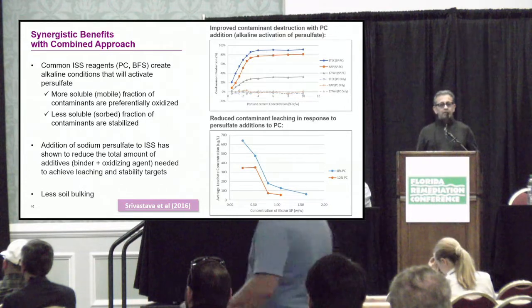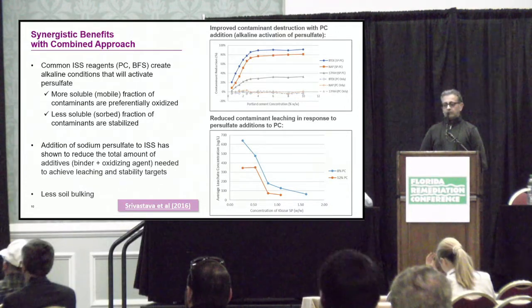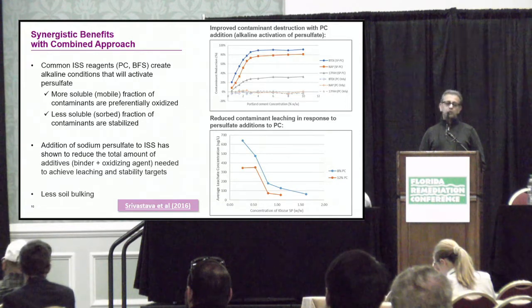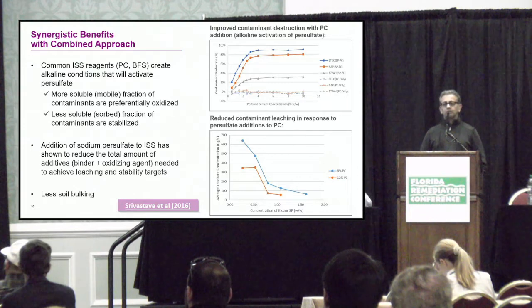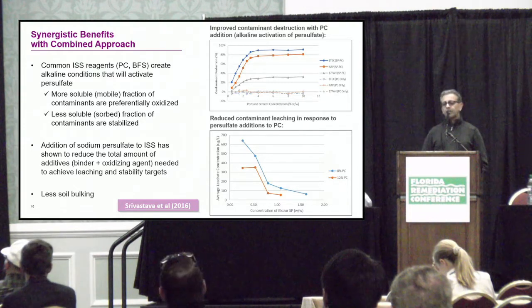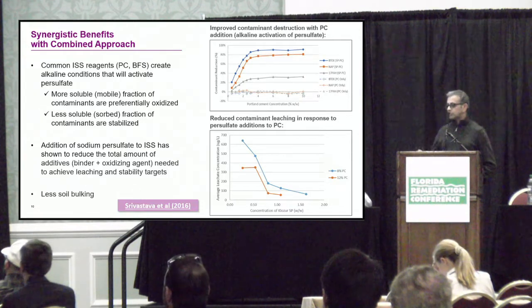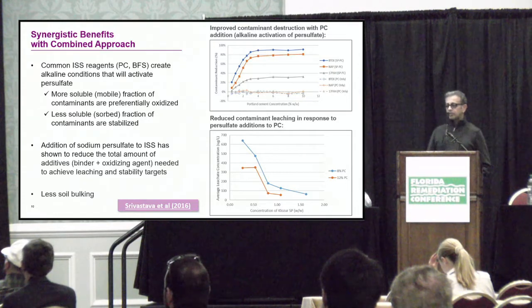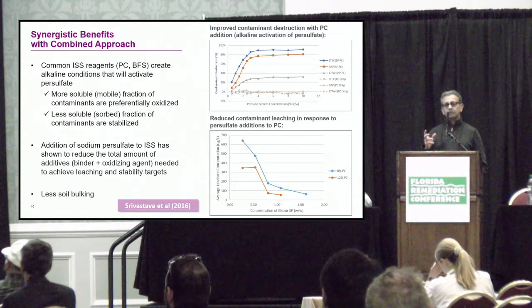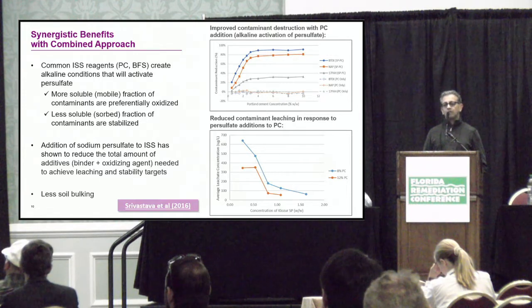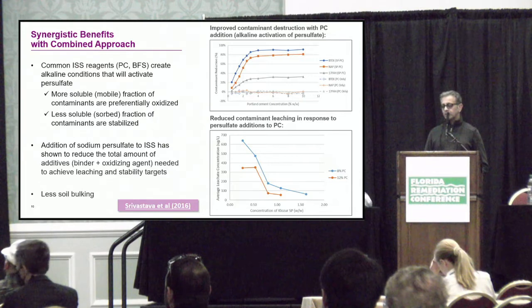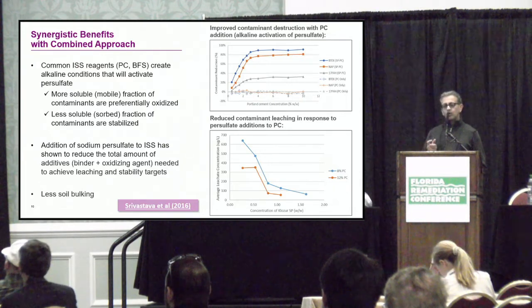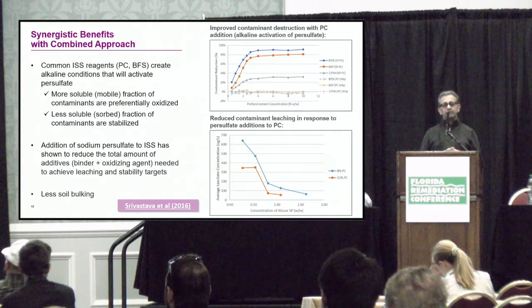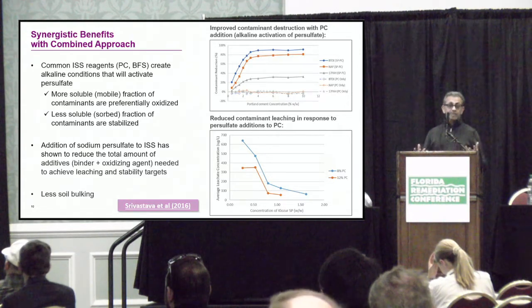So what happens when we combine the two technologies together? This was in 2016, Srivastava et al., who is now with Burns and McDonnell. He did a lot of the initial work in the lab to demonstrate that combining the two technologies has a lot of merits. And this slide presents some of the data from his study. Essentially, the more soluble compounds are first preferentially degraded, and the less soluble or less available contaminants are entrapped and stabilized in the ISS matrix. He also demonstrated that adding small amounts of persulfate to the ISS mix reduces the total amount of amendments or reagents needed, and hence there's less bulking of the soil.